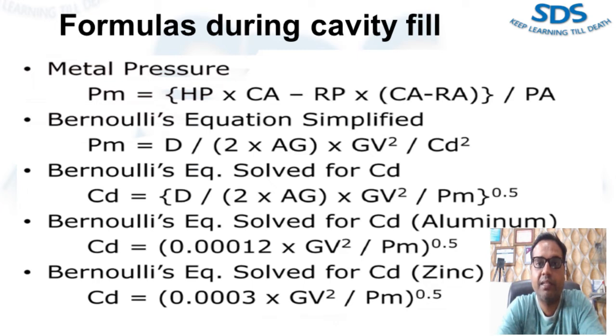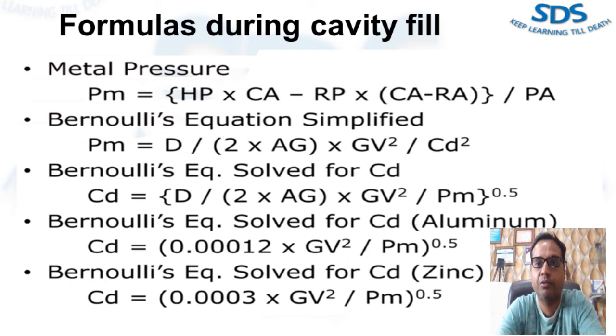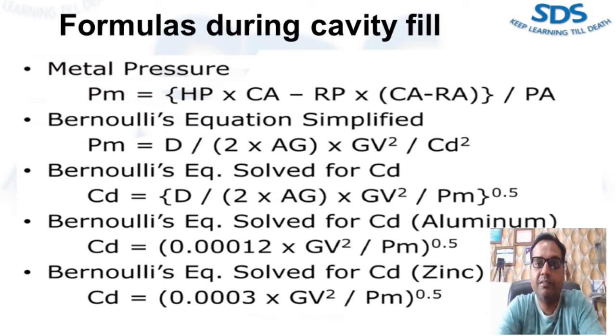If the Cd falls below the minimum, it indicates that excessive shot end force is required to achieve the desired fill velocity. This may result in lower than desired fill time or flashing problems. If you are able to calculate the Cd value in your die casting process, you can easily predict why your die is flashing or why you need higher force or higher pressure to achieve the desired fill time.